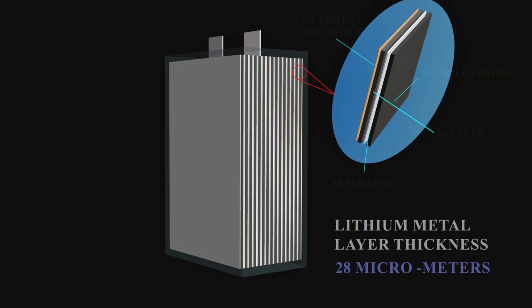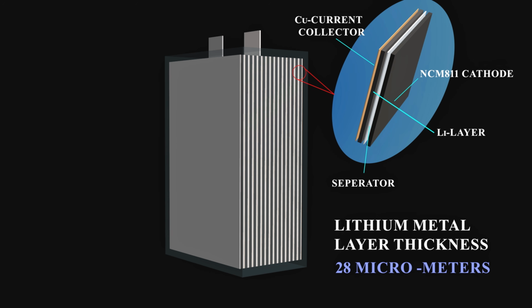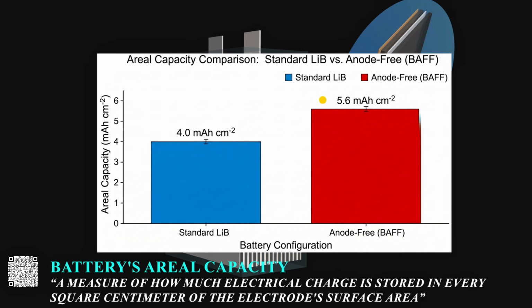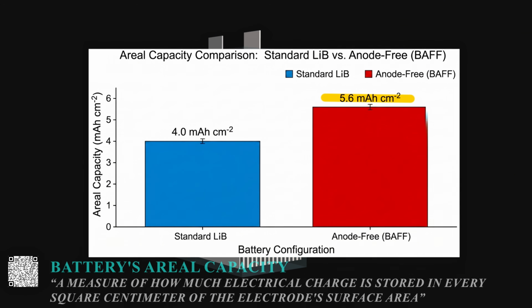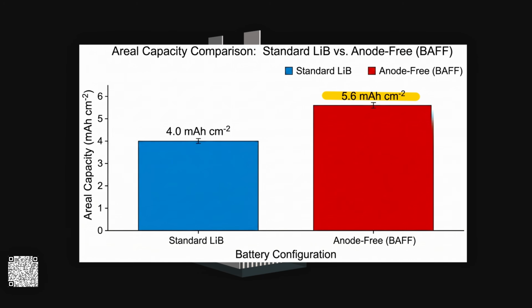A lithium metal layer, exactly 28 micrometers thick, contains no active anode material, yet it can hold 5.6 milliamp hours for every square centimeter of its surface.